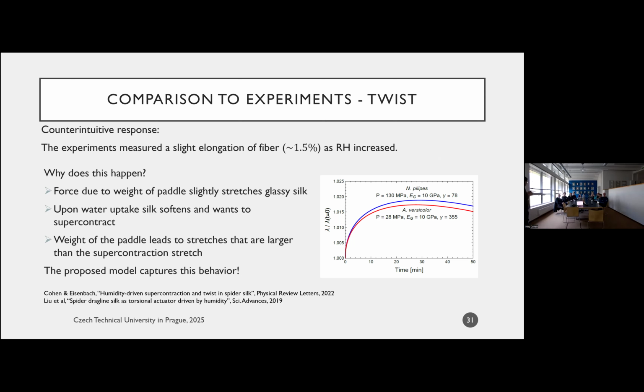And it turns out that the reason why they measured an elongation is because when water diffuses into the fiber, it wants to supercontract, but it also softens. And there's a weight that's attached to it. And that weight, if the fiber is very stiff, is going to do very little. But if the fiber is very soft, it's going to do a lot, right? And so because of the softening effect, we still end up seeing some sort of a minor extension here, right? And so this kind of forced us to think about this. But after we thought about it, we said, let's plug this into the model and see if our model captures this, because we didn't look at the longitudinal elongation until then. And it turns out that our model does a decent job, right? It does capture some sort of an elongation here.